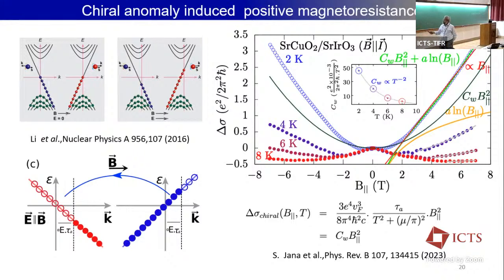So what is it about? If you have a Dirac semi-metal, when you apply a magnetic field, the Dirac node breaks into two Weyl nodes with different chirality. Now when we apply an electric field, what happens? One of the nodes gets populated compared to the other, and because of that you have an axial current. This is called the chiral current, and it follows a quadratic dependence on the applied magnetic field. The chiral population varies with the applied electric field, and tau is your chiral relaxation time.